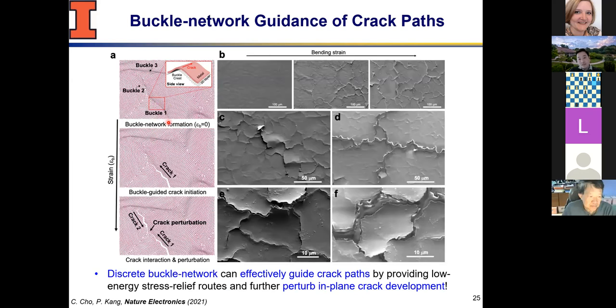And what's interesting is as you keep increasing the strain, these buckles basically guide the fracture of the gold. Because of the local strain on the apex of these buckles, you start to guide the cracks. And what's interesting is since these are never straight, never like the one that you see in the bare gold, you start to see very much an interaction between these buckles or cracks. And at the same time, because of this irregular structure of the metals, you start to see some bridging effect happening between these irregular islands. And we think that's the main reason how the electrical properties can be maintained.